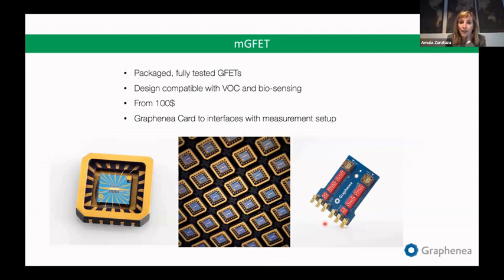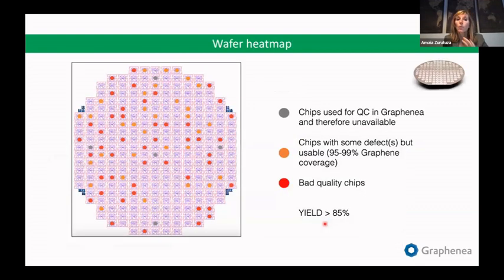We fabricate the devices at 6 inches, so 150 millimeters, and of course we do quality control. We measure optically but also electrically, and we obtain this type of heat maps for qualifying the wafers and also identifying individual chips that are not good. We also offer a graphene foundry service now.